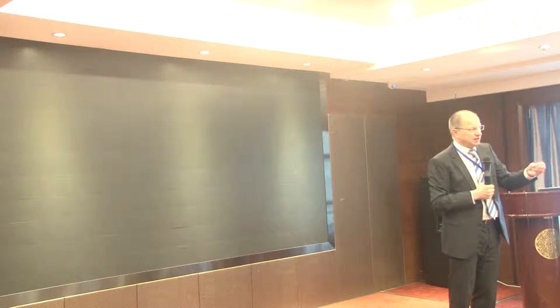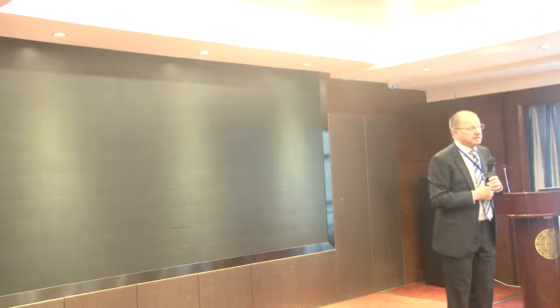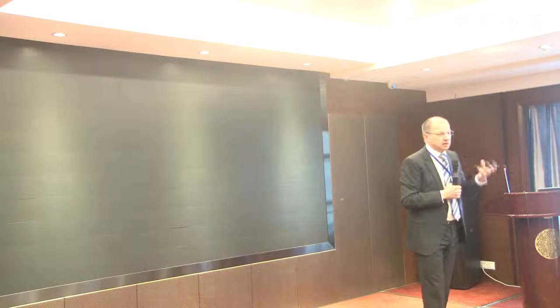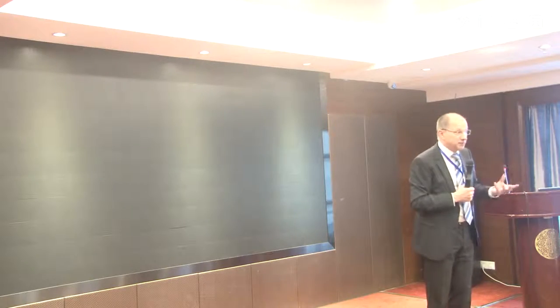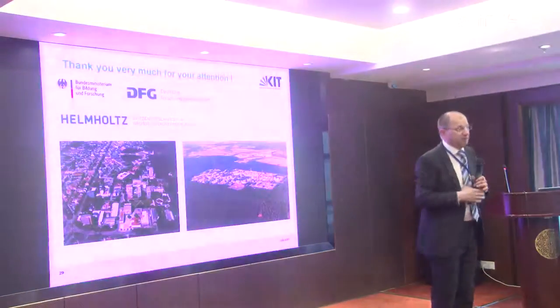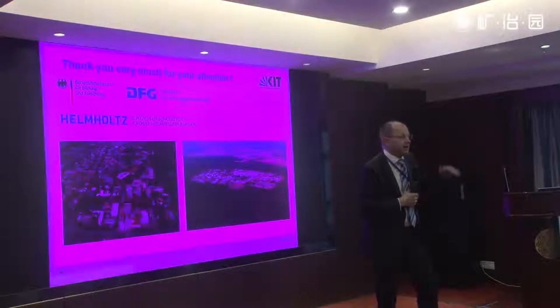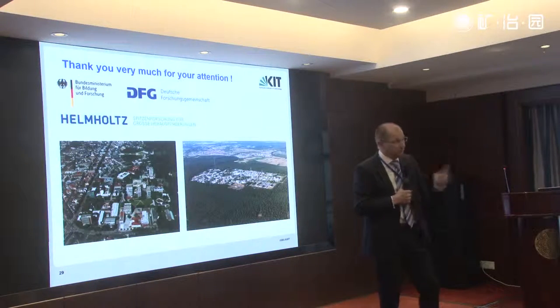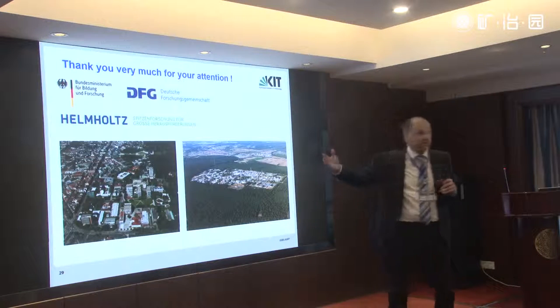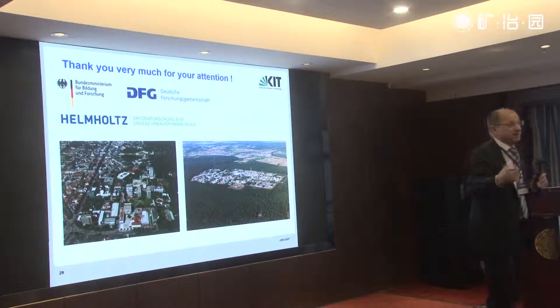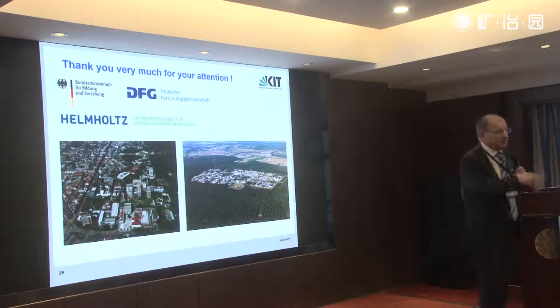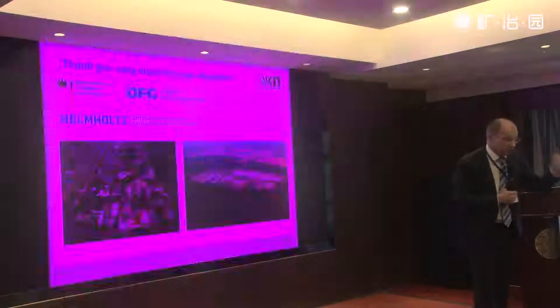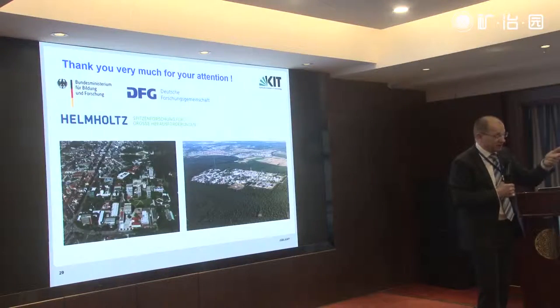The other question, I think you are raising, is the chemical composition. In that case, we do investigations by microprobe EPMA, using very extended and high-level standards to really find out the chemical composition and the ratio of chromium to zirconium. In the background, I could not show all the results. We do a lot of analysis, and many different departments help us to understand the crystallography, chemical composition, mechanical properties, and so on.